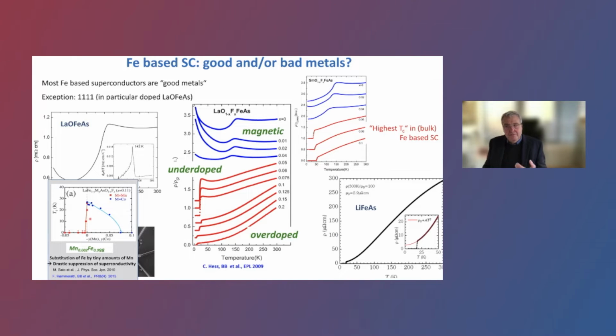So that's really a completely different situation than we have in lithium iron arsenide, far away from a good metallic state, very close to a localized state. I admit that I do not know a reason for that. If you ask the theoreticians, they will tell you, okay, electronic structures are very similar. There's no reason for that. The crystal structure of these layers is very similar.